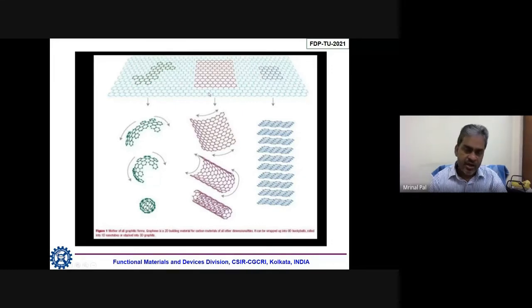It is again possible, if you roll it, to prepare from the same graphene a single layer nanotube. So in the case of the C60 buckyball, it is a kind of molding, and in the case of this nanotube, it is a kind of rolling of the graphene sheet. And this is a graphite structure, which is nothing but stacking one layer on another layer. So from graphene, you can prepare all the members of the carbon family very easily. You either have to mold, roll, or stack one layer on another.